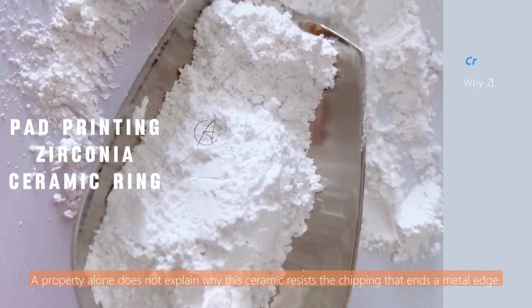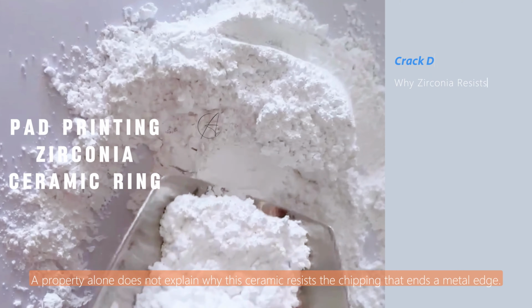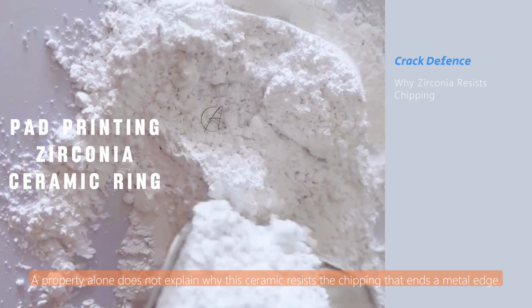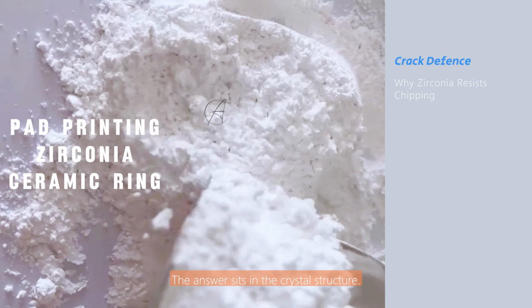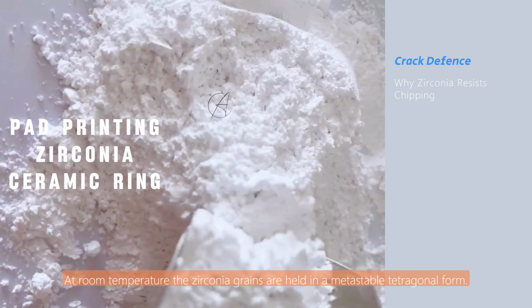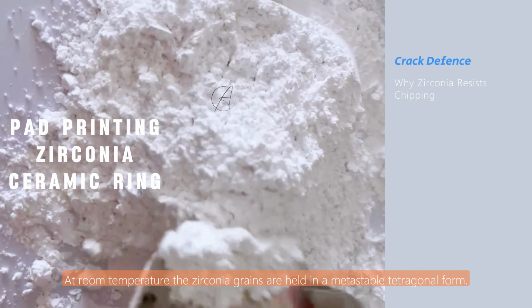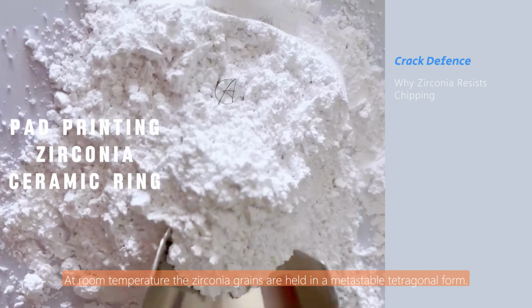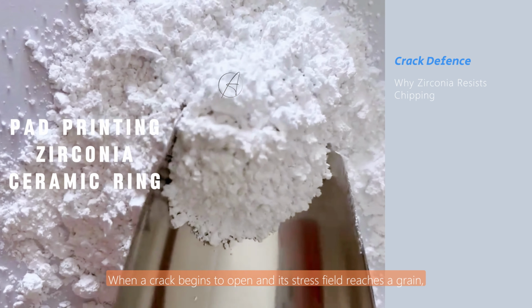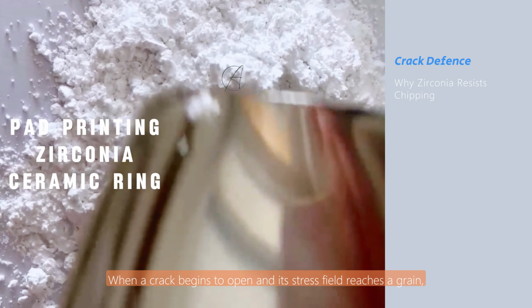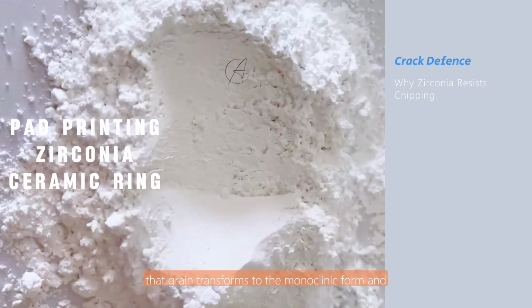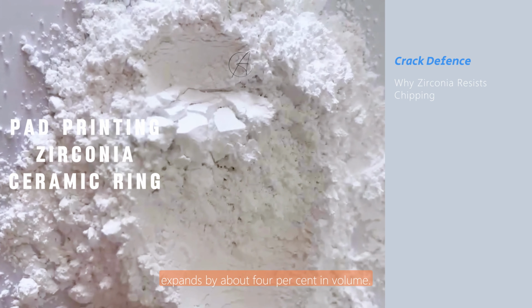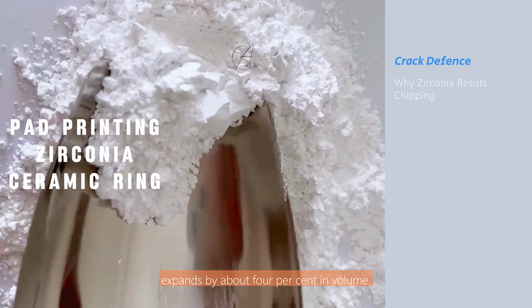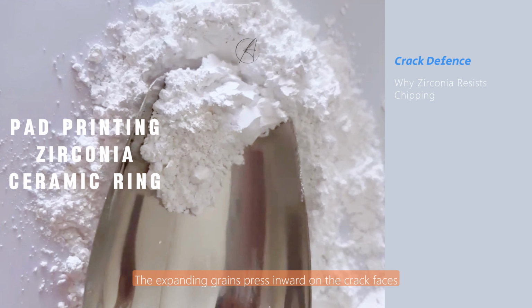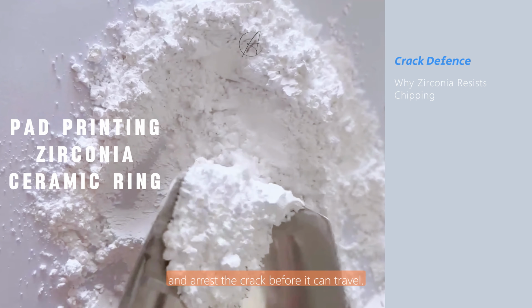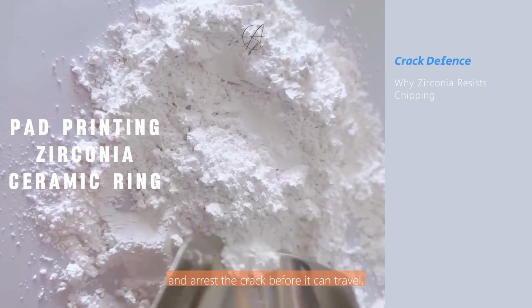A property alone does not explain why this ceramic resists the chipping that ends a metal edge. The answer sits in the crystal structure. At room temperature, the zirconia grains are held in a metastable tetragonal form. When a crack begins to open and its stress field reaches a grain, that grain transforms to the monoclinic form and expands by about 4% in volume. The expanding grains press inward on the crack faces and arrest the crack before it can travel.